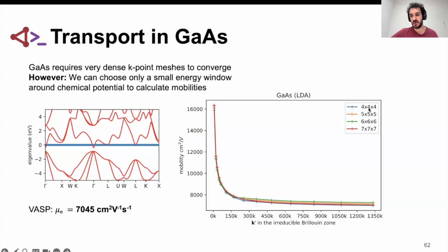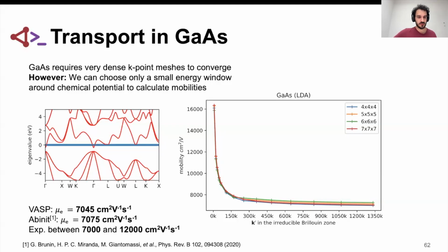The different colors are using different supercell sizes to compute the electron-phonon potential, and we obtain a mobility of 7,045 centimeters squared per volt per second. The results with Abinit are very close.